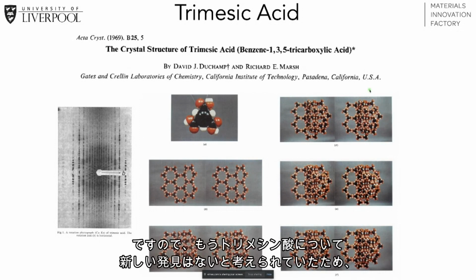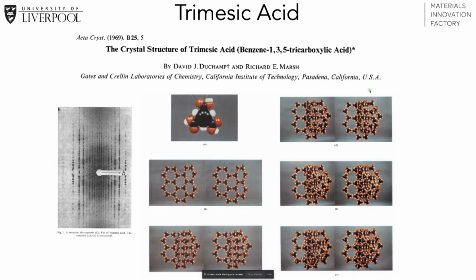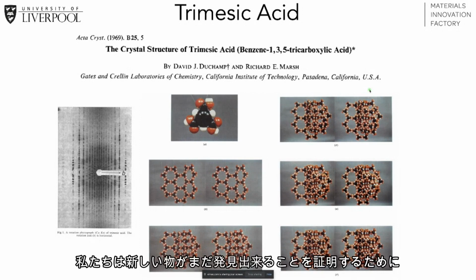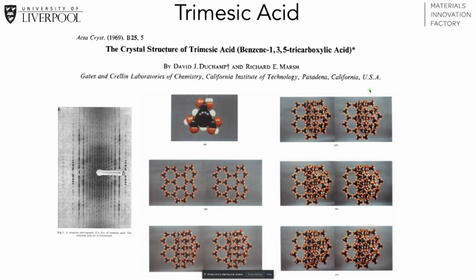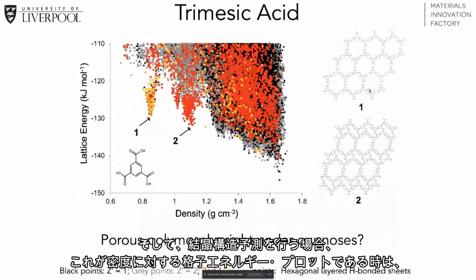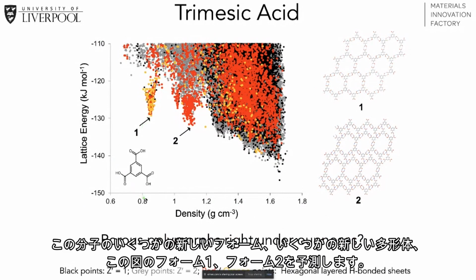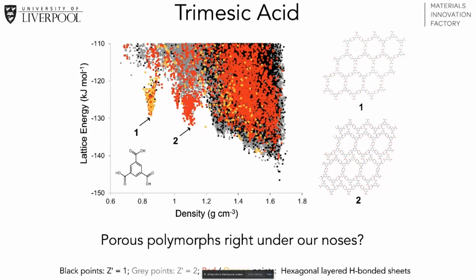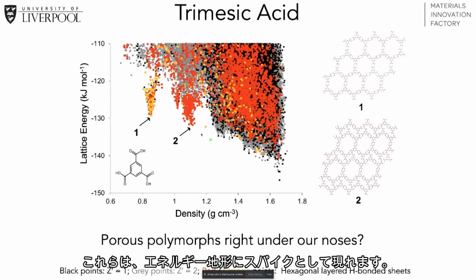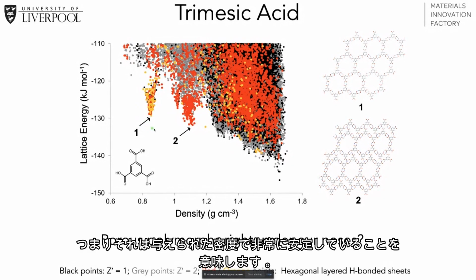And we deliberately chose it on the basis that there might not be anything new to find out about trimesic acid, because it's been studied. There are hundreds of papers. So we chose it specifically for that reason, to prove the point that you can find new things. And sure enough, if you do crystal structure prediction, and this is the lattice energy plotted against the density, we predict some new forms of this molecule, some new polymorphs, form 1 and form 2, and they emerge as spikes on the energy landscape. That means they are unusually stable at the given density.